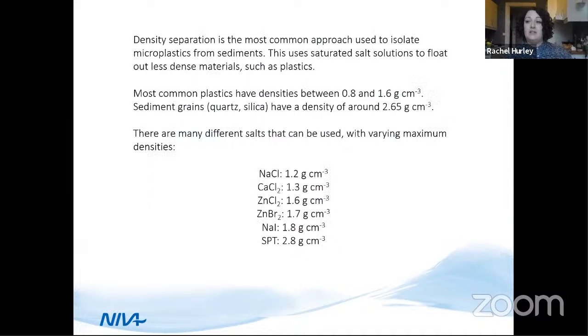So a few different techniques have been used to achieve this sediment separation. Some of these include elutriation using air and water, or the use of electrostatic devices. But by far the most common approach is to perform separation using density. This uses salt solutions, typically at their saturation point, to float out less dense materials, including the plastics. Most common polymer types that are used in products and found in the environment have a density of between 0.8 and 1.6 grams per cubic centimetre. Sediment grains are more dense, typically around 2.6. That's with quartz and silica. Therefore, we can use solutions with densities between these two values to extract microplastics from the more dense solid matrix.